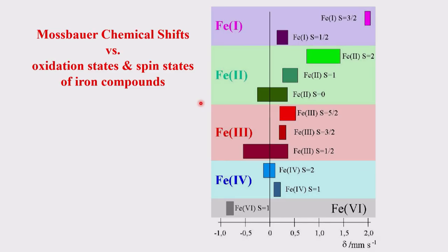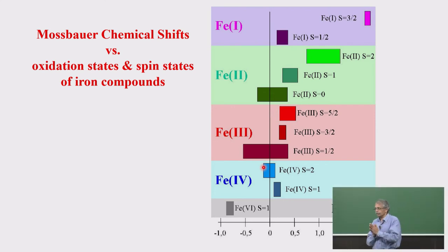So what we have learned from all these examples, we saw as the iron oxidation state is smaller and smaller, the more positive. Iron 1 is more positive as compared to iron 2, as compared to iron 3, as compared to iron 4. Again, your spin value, but I have not stressed much on that, so you don't need to worry so much. So in effect, you can say that the Mossbauer spectrum is dependent, one, on the iron oxidation state, and the second is the magnetic state or spin state of this. So both of these are the ones which define and derive explaining all these things.